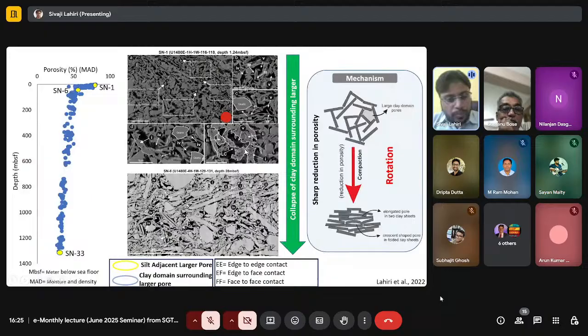Clay domain surrounding pores means, maybe I can try to share here. Here you can see there is a very big pore, and surrounding it lots of clay particles are present. You cannot see any silt particle. But here you can see a very big pore, and just adjacent to that there is a very big silt particle. We realized that these 2 types of pores play a very critical role, because when we look at samples from around 28 MBSF, or 28 meter depth, this sample does not have too many of these larger clay domain surrounding pores. Then we realized that these pores play a very critical role in the reduction in porosity at shallow depth. This is not unnatural with increasing effective load, because as you go deeper, effective load is increasing. This is quite natural, isn't it?